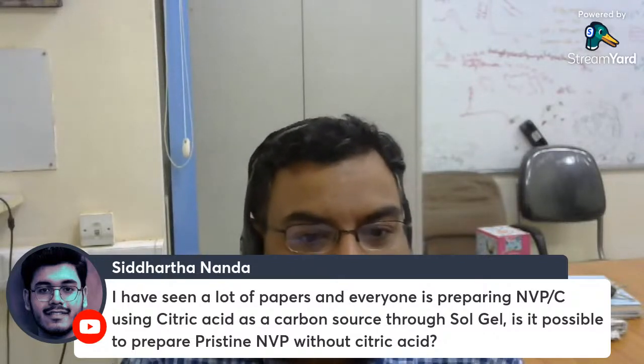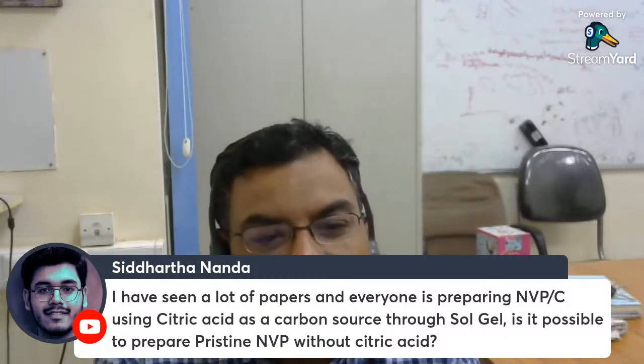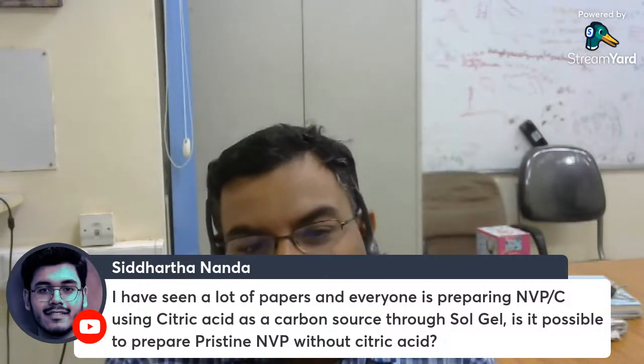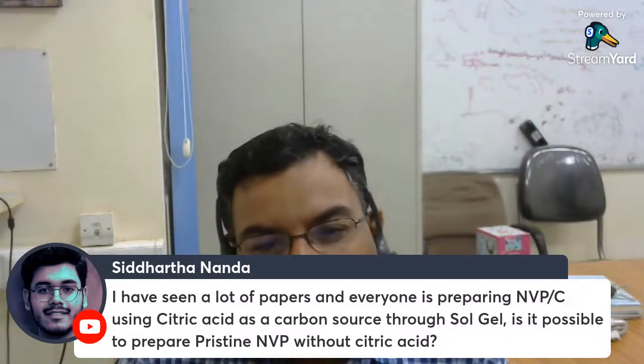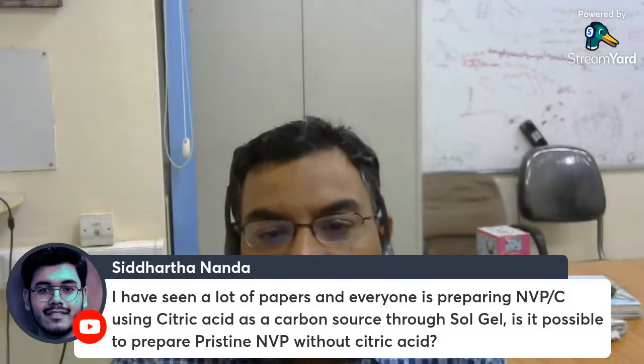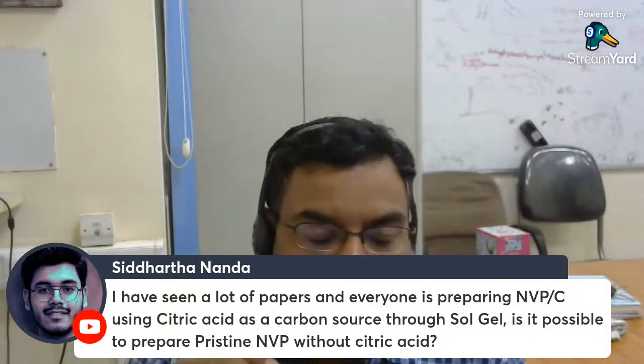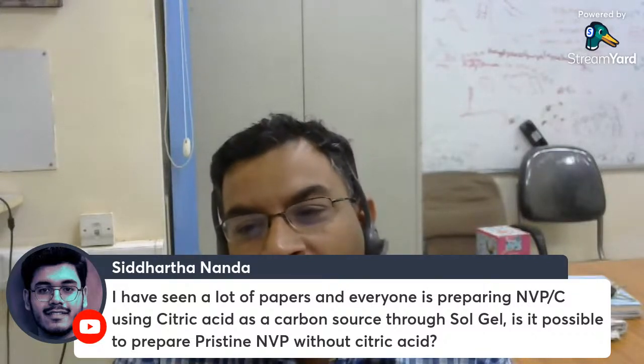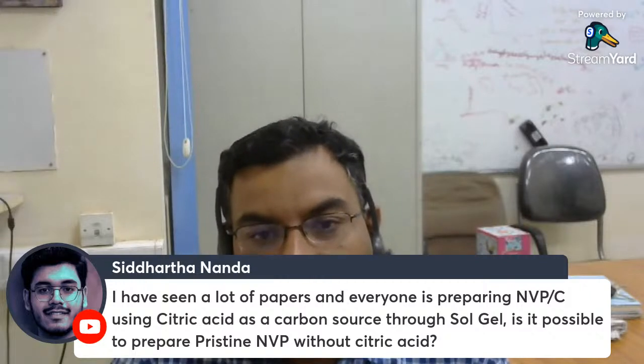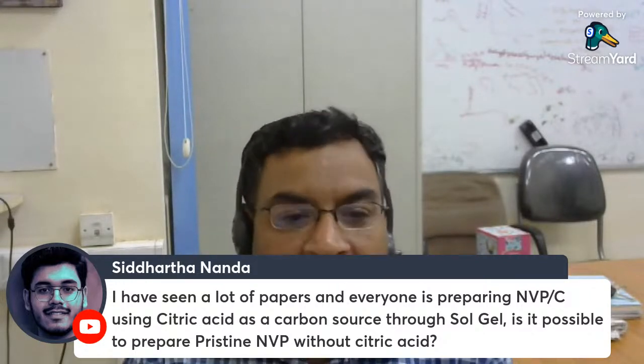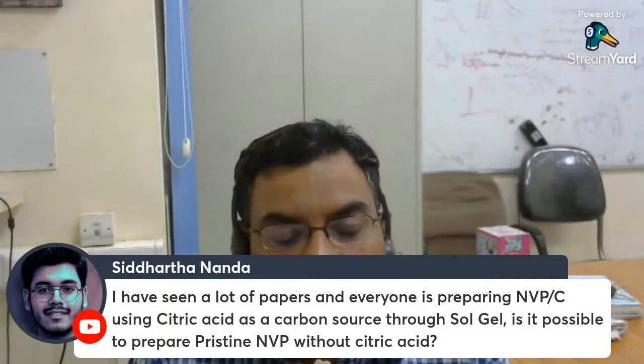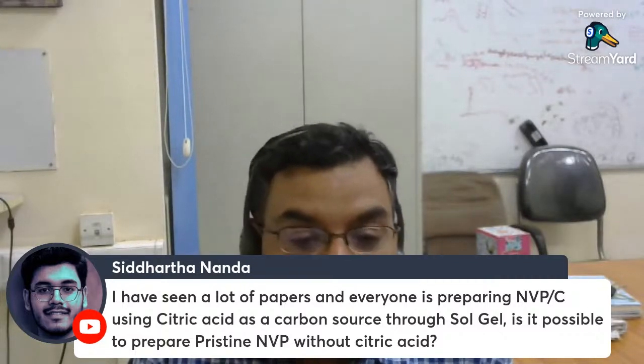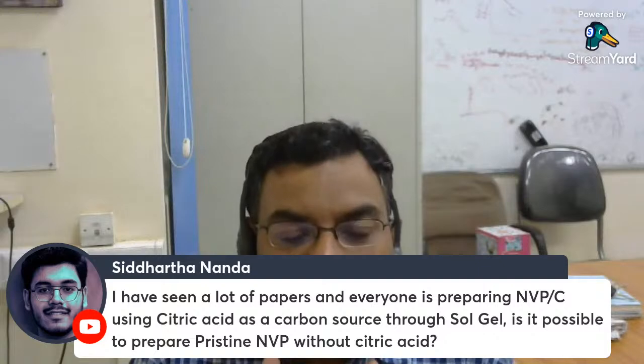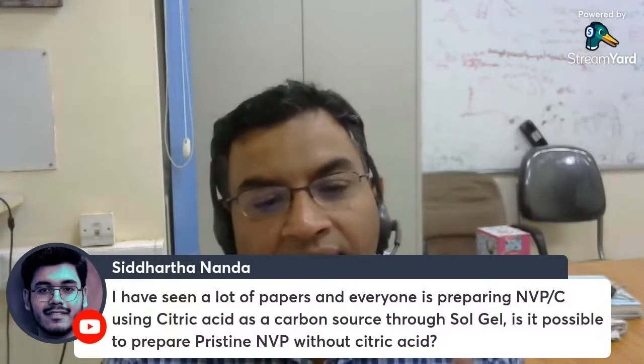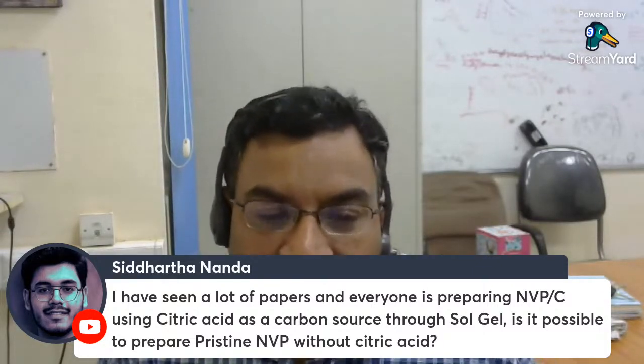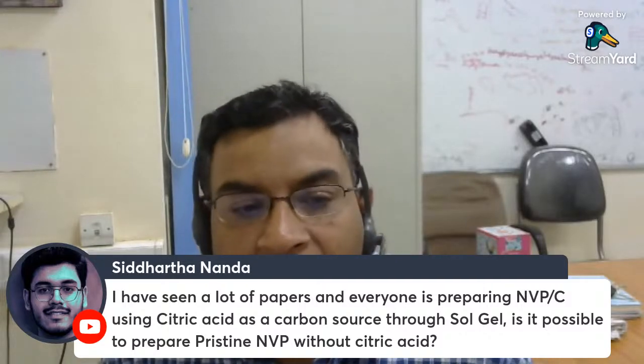There is another question. I have seen a lot of papers where everyone is preparing NVPC using citric acid as a carbon source through Sol Gel. Is it possible to prepare pristine NVP without citric acid? Citric acid is playing two roles. It is providing the residual carbon, and it is also acting as a chelating agent to get chemical homogeneity inside the material. So you can prepare pristine NVP, but you have to use some type of chelating agent. Instead of citric acid, you can try tartaric acid or oxalic acid.